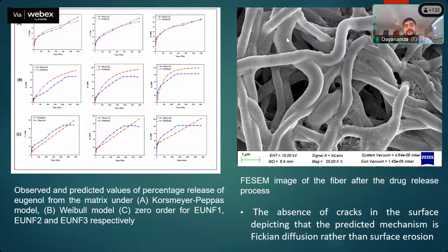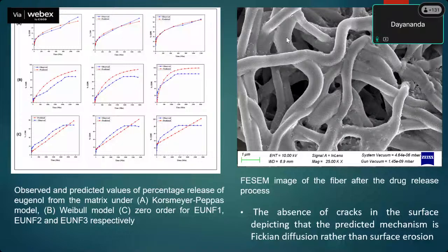Whenever you use it for real application, the loaded drug can come out through the network. It was found that the value of n gives an idea of how it comes out from the nanofiber mat, whether through diffusion method or surface erosion method. The absence of cracks on the surface depicts that the predicted mechanism is Fickian diffusion rather than surface erosion.